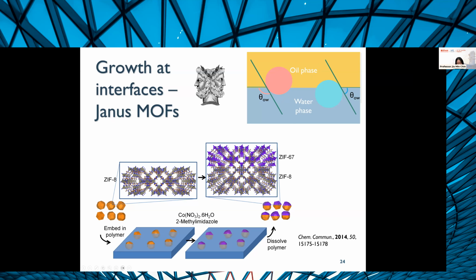Then we took this and did some further heteroepitaxial growth. We took cobalt nitrate and 2-methylimidazole to grow ZIF-67. ZIF-67 is isostructural to ZIF-8, but you use cobalt instead. The reason we did this was because cobalt is redox active, and it could be used for a Fenton-like reaction for the breakdown of hydrogen peroxide. And so one could use this for micromotor movement.